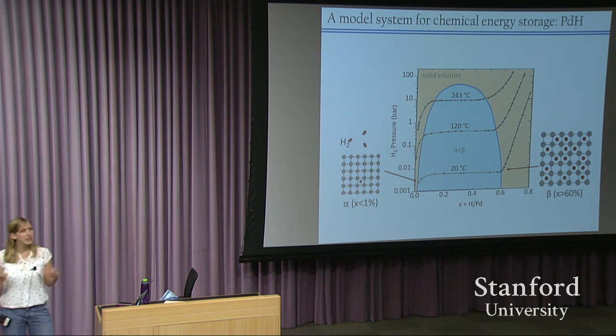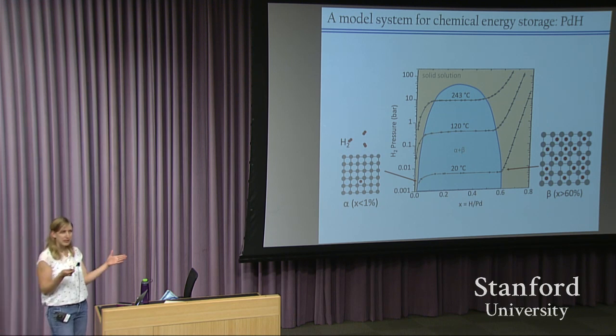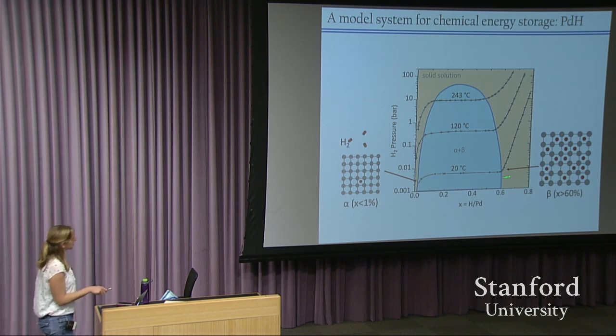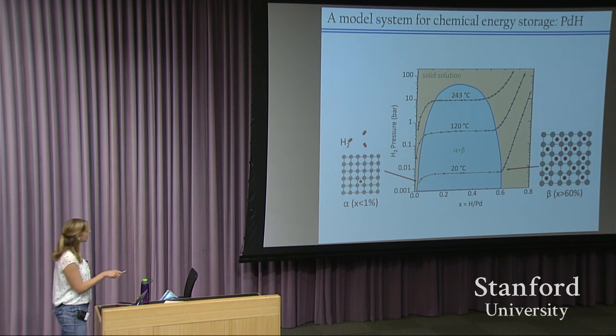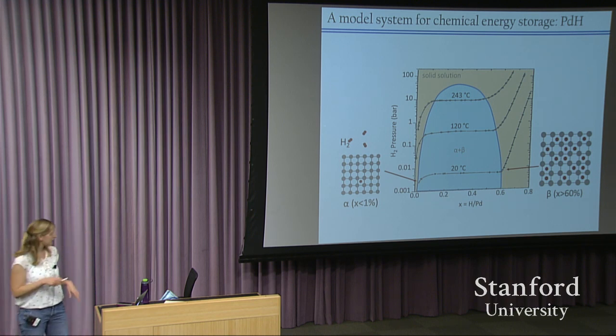So in bulk, the volume expansion is about 3% in lattice constant, so about 10% in volume. So there's a pretty significant volume expansion associated with this phase change. And then I'll also mention that in between the two phases, you have this coexistence region in bulk, so coexistence of alpha plus beta.